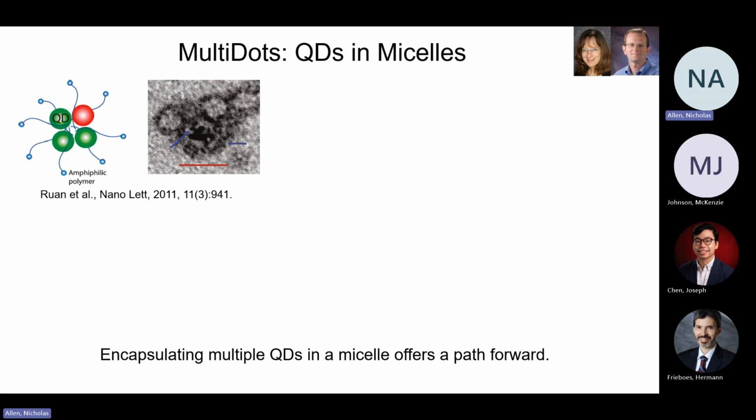Another is easy to see. So one of the solutions that we came up with was to encapsulate particles in block copolymer micelles. And the reason is a block copolymer is pretty long, and that provides a really thick coating, which should protect the particle. But our innovation was that we were able to encapsulate multiple particles within the same micelle. So even though it ended up being about the same size as the ones that are commercially sold with really thick polymer coatings, it's brighter, so there's more particles in it.